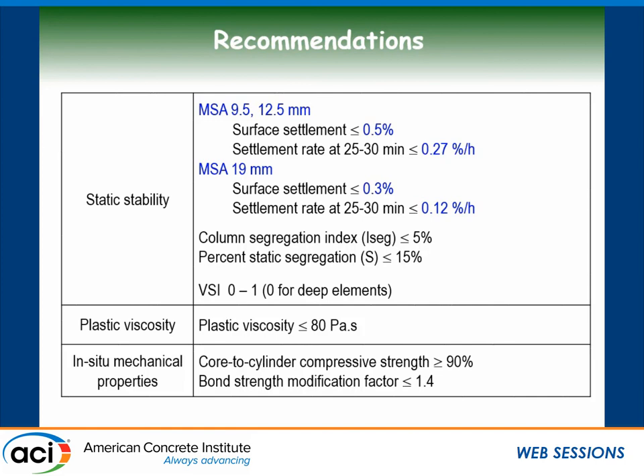And here we are giving some recommendations. This is NCHRP results. If you're using 3/8 aggregate, half-inch aggregate, your surface settlement should be less than or equal to 0.5% of the sample height. And if you're doing rate of settlement after 30 minutes, that number should be 0.27% per hour of settlement. If your aggregate size increases, then you have to build more viscosity to suspend your aggregate, and your surface settlement should be less than 0.3, rate of settlement 0.12% per hour.